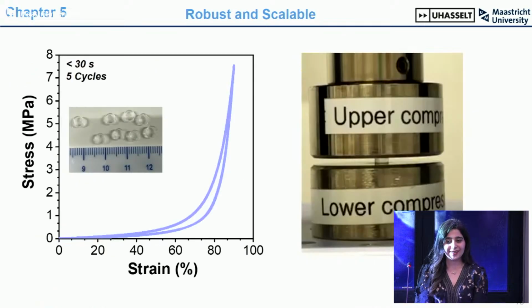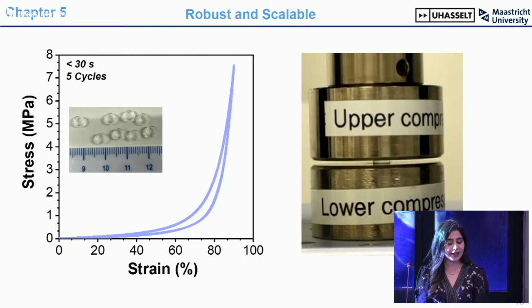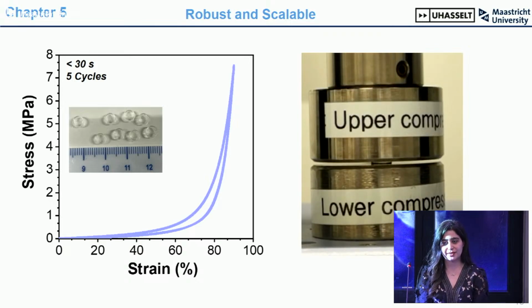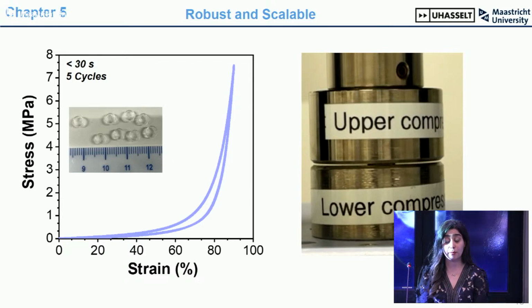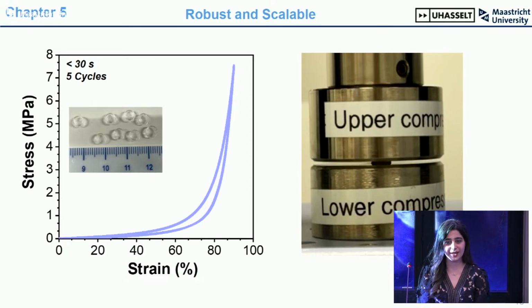Volumetric printing in general is very powerful. It allows for scalability, meaning that I can print multiple of the same structure at the same time. Like all these 8 disks, I printed them at the same time in less than 30 seconds. They are also very robust, meaning that I can compress them to 90% of their initial height multiple times, and they don't break. They remain intact.